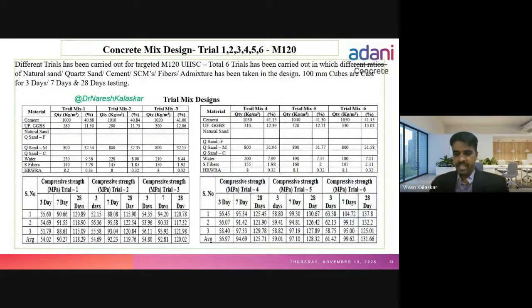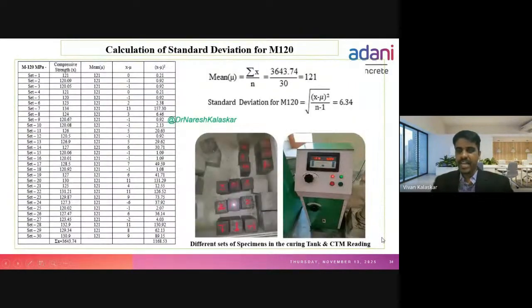This is M120. You can see here in the previous mix we have used quartz sand and finer quartz sand. In this mix we have used medium quartz sand and coarser quartz sand. Both the finer quartz sands have been omitted, and only medium quartz sand we have used. And when we have used only medium quartz sand and also omitted natural sand, we got 131.66 MPa for M120. The standard deviation for M120 is 6.34.